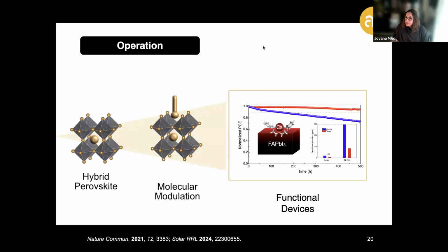This can be monitored by analyzing the resulting solar cells in the presence and absence of different modulators, continuously radiating them over time and monitoring their power conversion efficiencies, comparing the treated systems in red to conventional perovskites in blue. We see the benefits of relying on these systems to stabilize performance over time, even in formamidinium lead iodide perovskite compositions that are attractive for their optoelectronic characteristics but notoriously unstable.